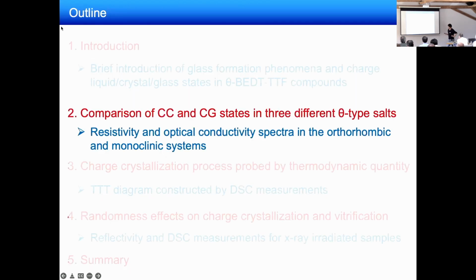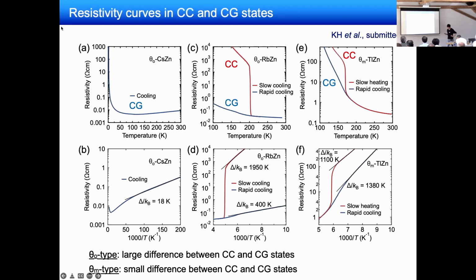Okay, so first I will show the comparison of charge crystal and charge glass states in three different compounds. Here are the temperature dependences of the three different materials: orthorhombic cesium zinc and rubidium zinc, and the monoclinic thallium zinc compound. The theta-cesium zinc compound, with the most isotropic triangular lattice, shows no long-range charge ordering down to very low temperature, and the system enters the charge glass state at low temperatures.